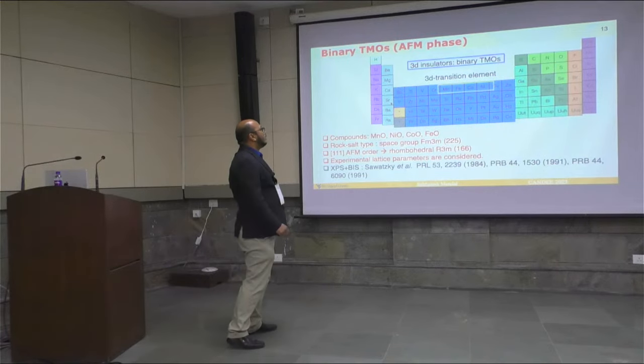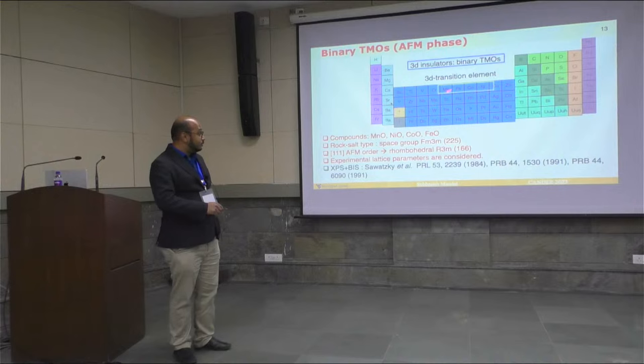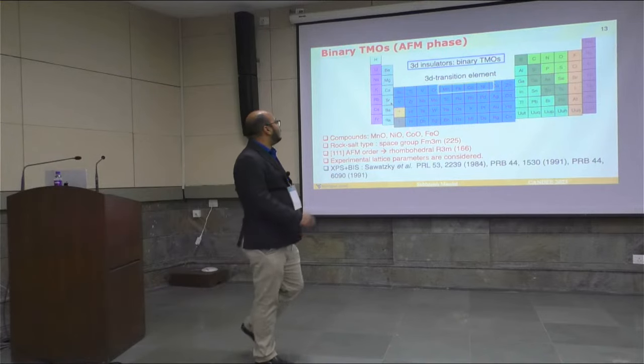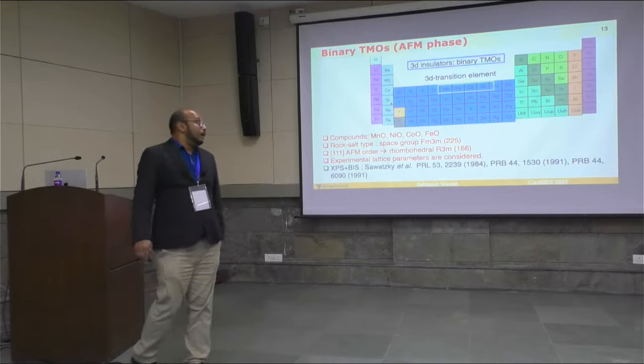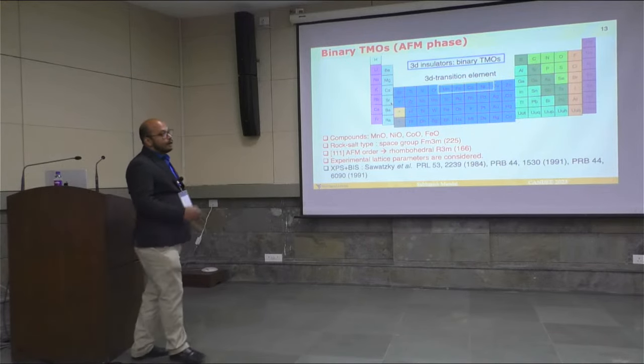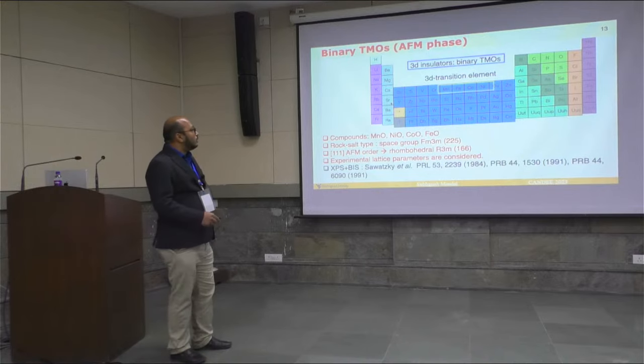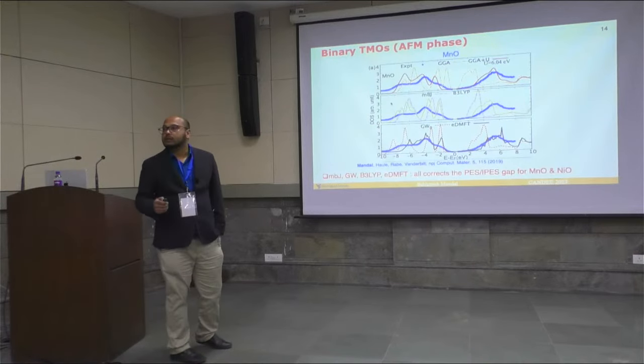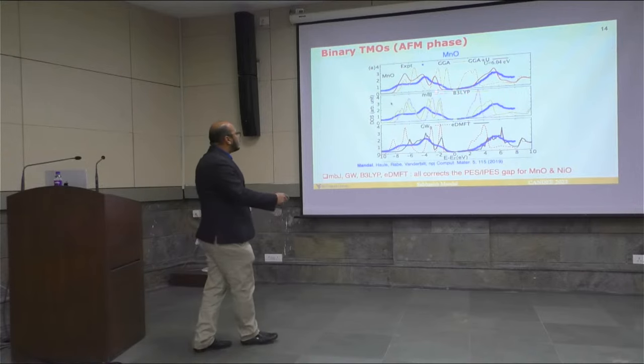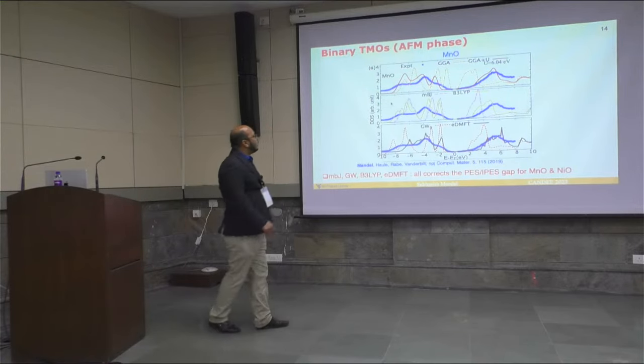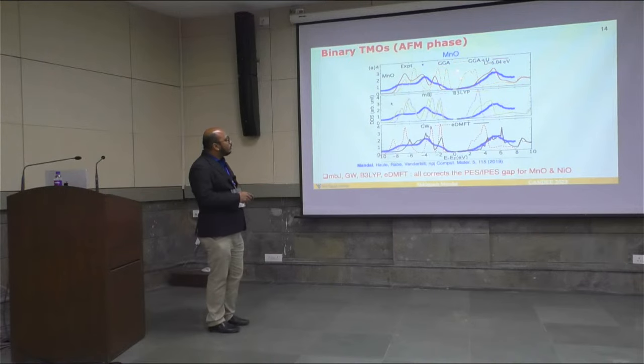The first set of materials is binary transition metal oxides, consisting of, say, iron oxide, nickel oxide, cobalt oxide, and manganese oxide. They are insulators, and we're talking about the antiferromagnetic phase. Then we're going to compare with the experiment, photoemission experiment. The blue dots are the photoemission and inverse photoemission experiment. And for MnO, GGA reduces the gap. It does not have the proper gap. But if you put some U, which is a tuning parameter, you can actually get a good match.